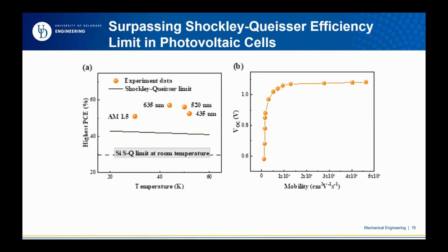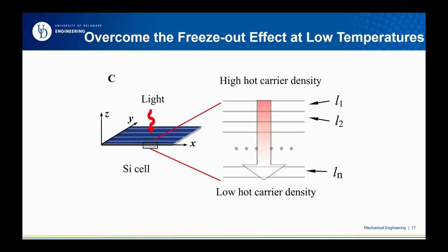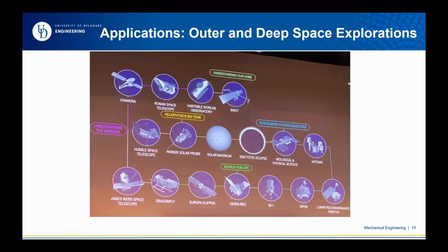I forgot to mention that this is the SQ limitation at room temperature; it is temperature dependent, and we calculated it. All of these results are at different temperatures, at the highest output power. You can see here the open circuit voltage increases dramatically with the increase of mobility. I think to avoid the so-called freeze-out effect, you have to have light that can penetrate through the whole thickness of the solar cell. This is what we learned.